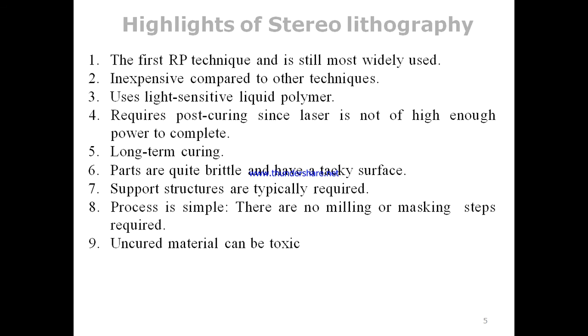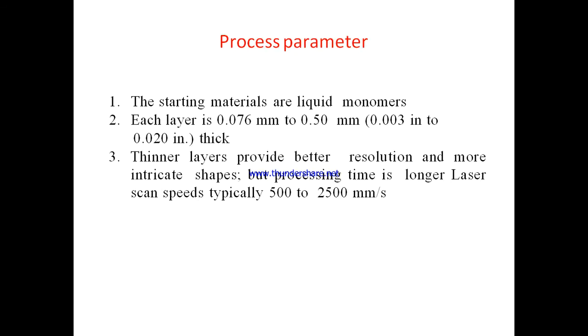still most widely used. It is inexpensive compared to the other techniques. It uses a light sensitive liquid polymer. It requires post curing since the laser is not of high enough power to complete the curing. So long term curing is required. Parts are quite brittle and have a tacky surface. Support structures are typically required for SLA. The process is simple and no milling or masking steps are required. Uncured material can be toxic in case of stereolithography.